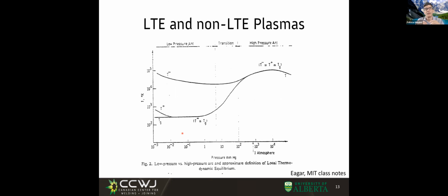That's why we call it thermodynamic equilibrium, which is a term that we also use in our heat transfer class, right? And they say local because in other parts of the arc, it might not be in thermodynamic equilibrium. But in this one part, in which the electrons and the ions can share their kinetic energy, we have thermodynamic equilibrium. Now, there are cases in which we don't have this local thermodynamic equilibrium. One of the cases is at very low pressures, because at very low pressures, the atoms start to get farther and farther apart from each other.